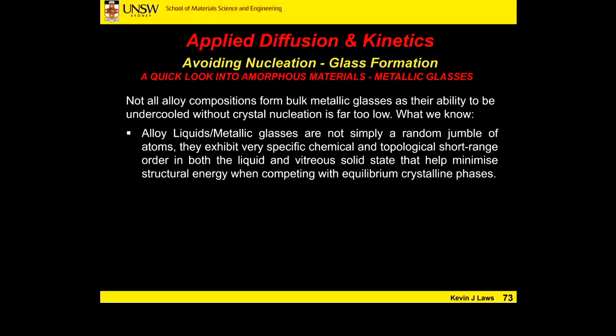Yeah. So basically, when we have a system where all the atoms are the same species, or the same size, diffusion becomes very, very easy. We essentially only have to break similar bonds for an atom to move. These bonds can be highly dissociated in the liquid state. And the packing of atoms that are all the same size, or spheres that are all the same size, actually isn't great.